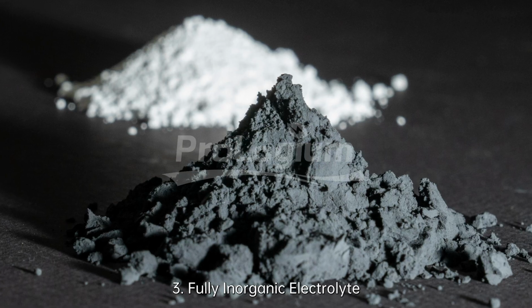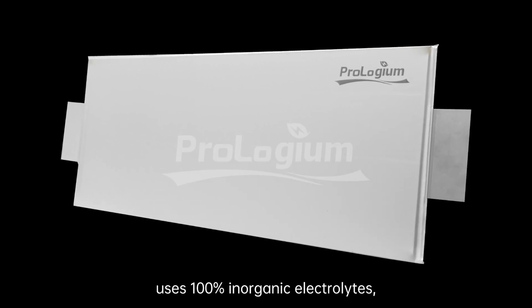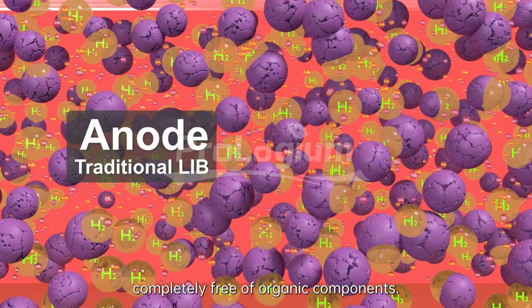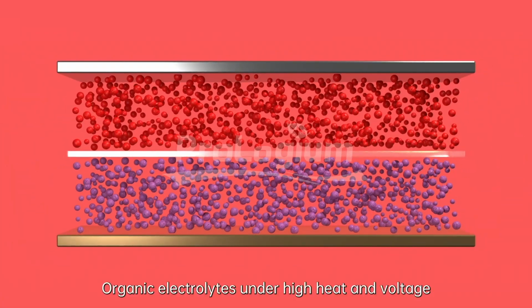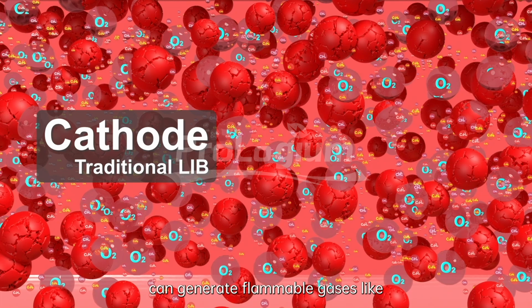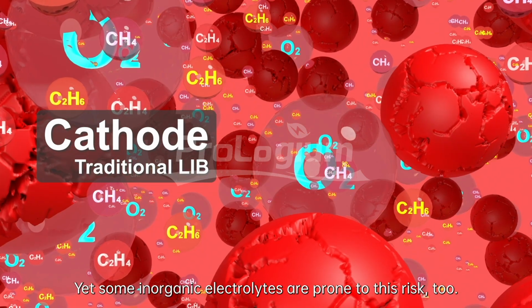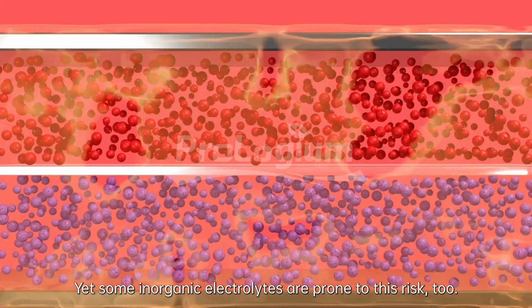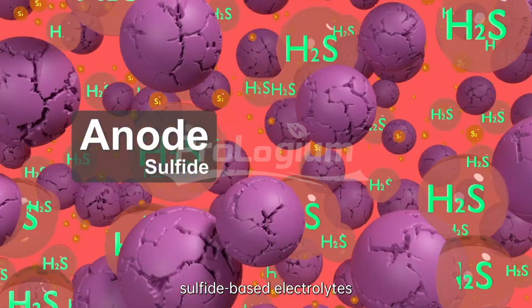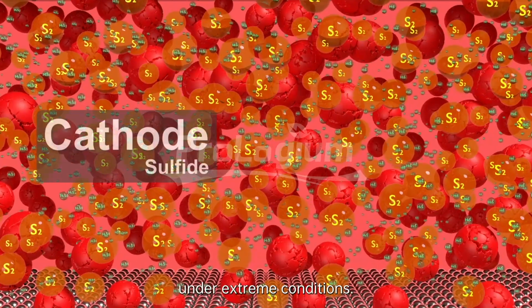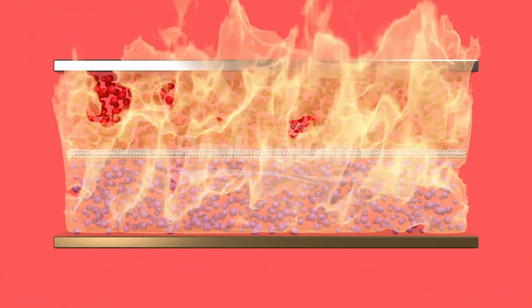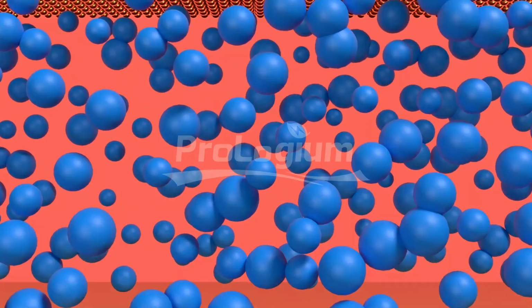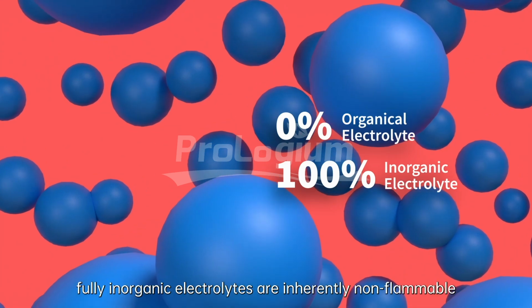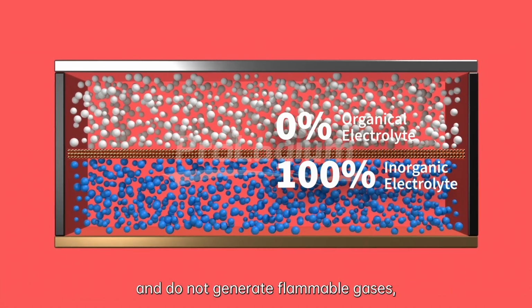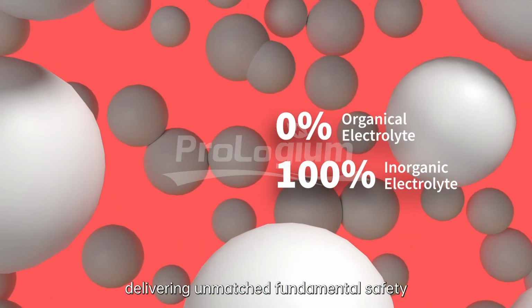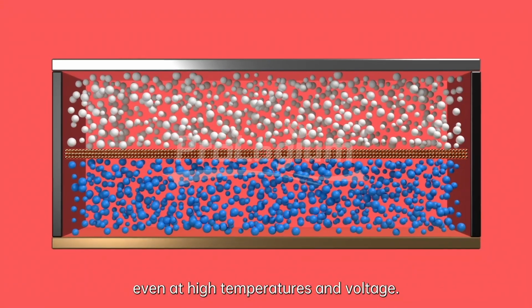3. Fully inorganic electrolyte. The fourth generation battery uses 100% inorganic electrolytes, completely free of organic components. Organic electrolytes under high heat and voltage can generate flammable gases like methane, ethane, and ethylene. Yet, some inorganic electrolytes are prone to this risk too. For instance, sulfide-based electrolytes can produce toxic, flammable hydrogen sulfide under extreme conditions. By contrast, ProLogium's 4th generation fully inorganic electrolytes are inherently non-flammable and do not generate flammable gases, delivering unmatched fundamental safety even at high temperatures and voltage.